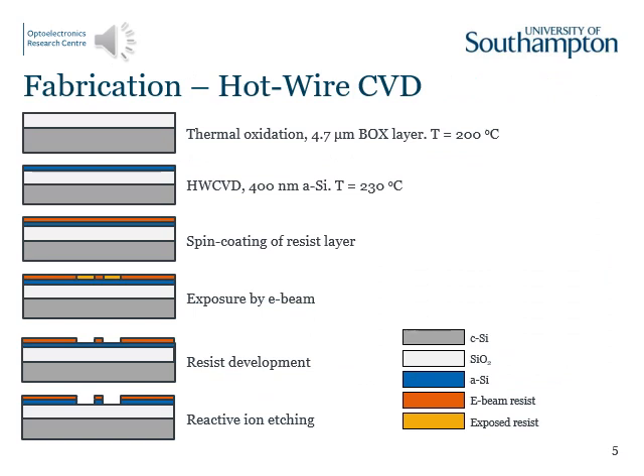To this end, we have carried out continuous wave laser crystallization of amorphous silicon deposited at low temperatures by hot wire chemical vapor deposition. The hot wire CVD process has been selected as it offers low temperature, high purity deposition of low hydrogen amorphous silicon with a low cost and high deposition rate.